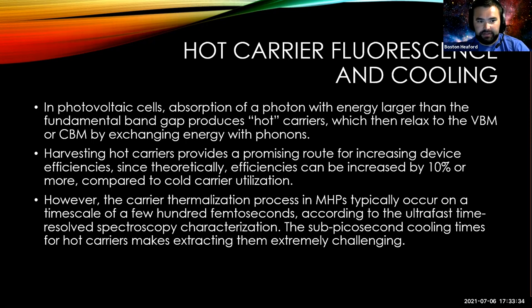However, the carrier thermalization process in perovskites typically occurs on a time scale of a few hundred femtoseconds, at least according to the ultra-fast time-resolved spectroscopy characterization. And the sub-picosecond cooling times for hot carriers make actually extracting them extremely challenging.